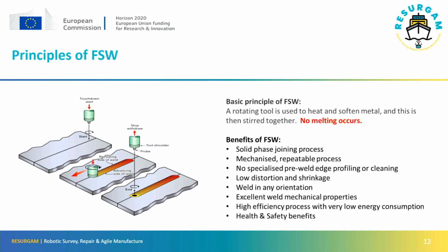All that the process involves is we have a rotating tool, which is very much like a blunt milling cutter. That's lowered onto the surface of the weld area, and we then move it along. It generates heat simply by friction, but the key thing is it does not melt the steel or the aluminium. It turns it into a very soft state, but it does not melt it, and then it mechanically stirs it together. So a lot of the defects and problems you get with conventional arc welding or laser welding or even electron beam welding, you do not get with friction stir, because you're not actually melting anything.